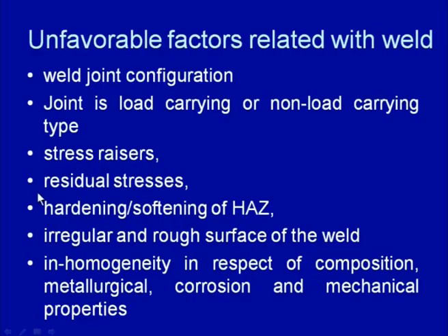So, surface hardening, like an increase in the hardness of the surface, will decrease the nucleation of the crack, especially in the heat affected zone and in the weld region, because of the increased number of cycles required for nucleation of the crack. But if softening takes place either in the heat affected zone or in the weld zone, then it will facilitate the crack nucleation stage because of the easy micro level deformation by slip.